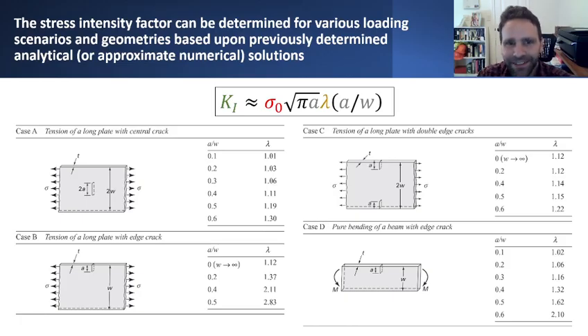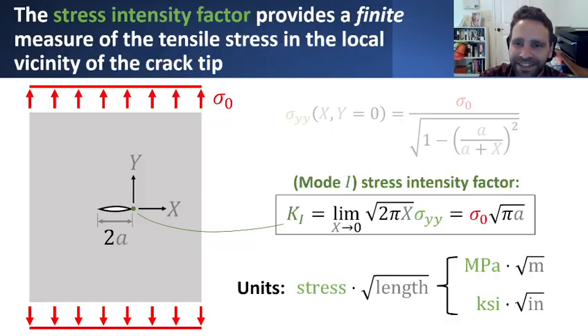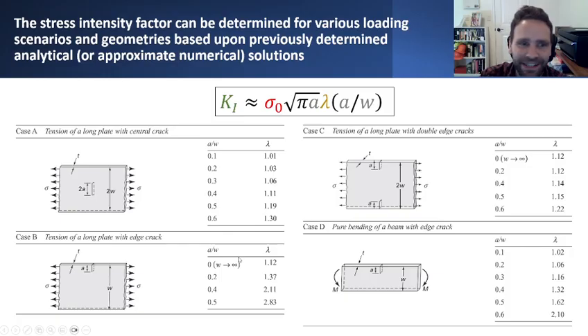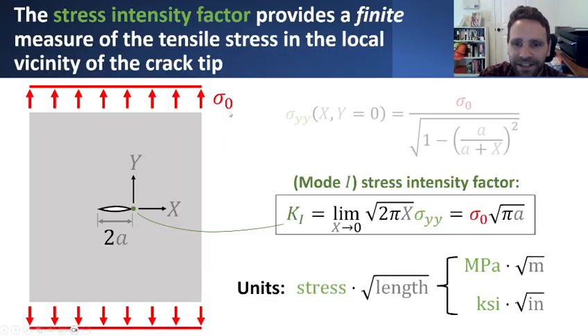So what's useful about the stress intensity factor is that we can come up with different values for what this stress intensity factor should be by looking at different solutions obtained for other interesting geometries and loading conditions. For this classical solution of an infinite plate with the far field loads of sigma naught and a crack of length 2a, the mode 1 stress intensity factor is simply sigma naught times the square root of pi times a. Very cool. But that's not true for all possible plate geometries and loading conditions. If you have a different loading scenario with a plate of finite width, or a plate with two cracks along the edges with finite width, or other interesting things going on, you can come up with different values for this stress intensity factor. And they're all still defined in this same way through this limit.